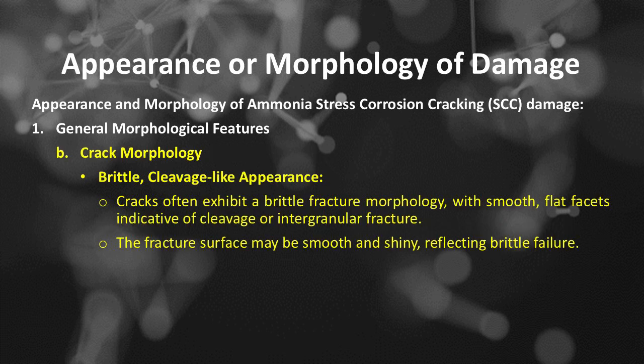General morphological features is crack morphology. For brittle, cleavage-like appearance, cracks often exhibit a brittle fracture morphology, with smooth, flat facets indicative of cleavage or intergranular fracture. The fracture surface may be smooth and shiny, reflecting brittle failure.